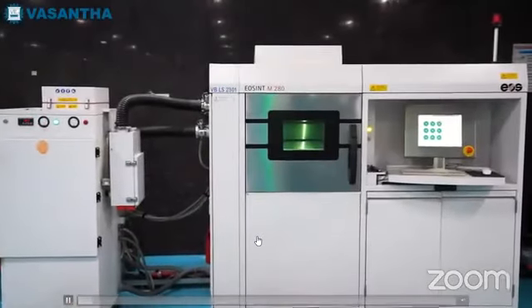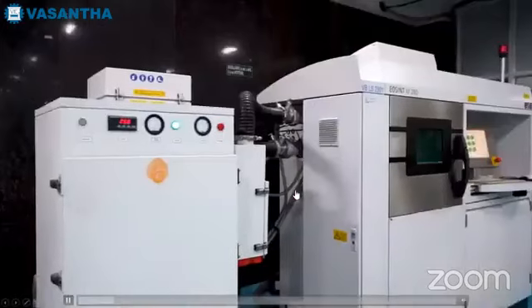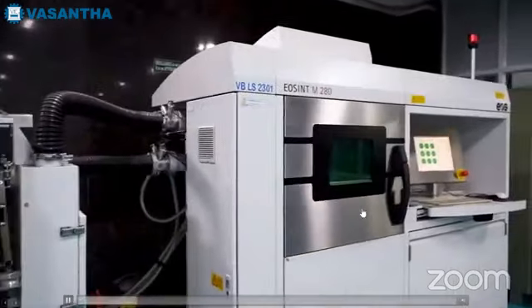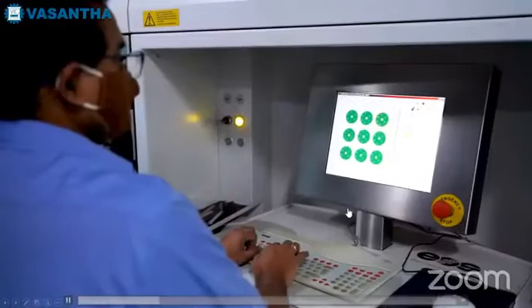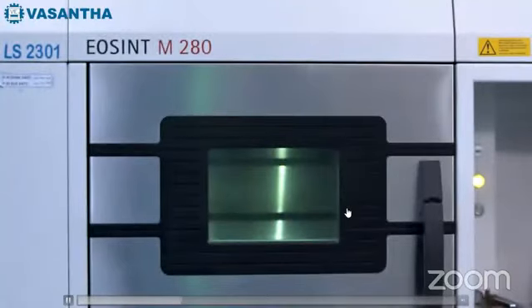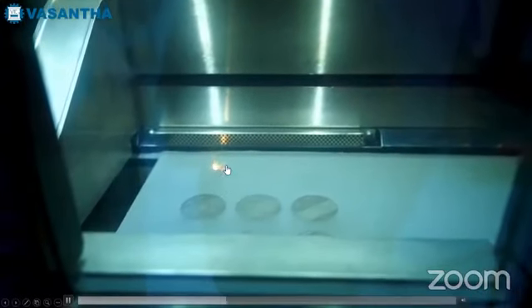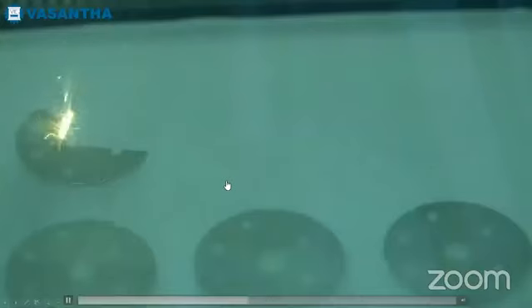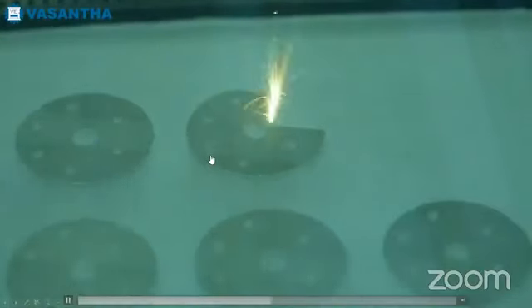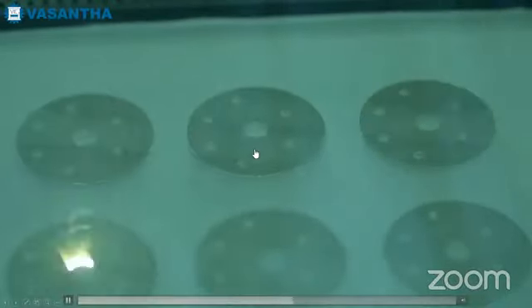Every layer will be about 40 microns, which will be shot by a laser, which burns only the area of the insert, and wherever there is no insert, like cooling areas, it won't burn. So we'll have a hollow space there. This is the powder, wherein through the laser we are burning the powder to make it solid. And you can see it leaves some spaces in between, which are the cooling channels.